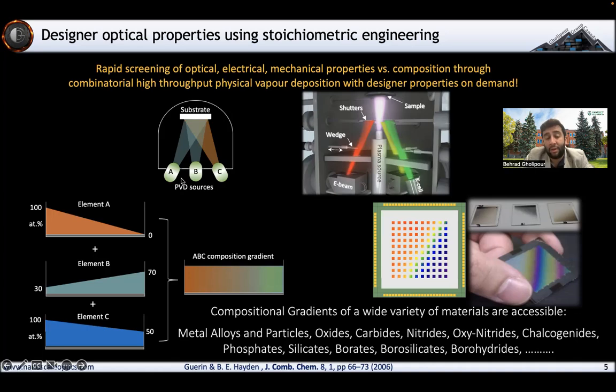So if you have a fictional material system, let's say ABC, by putting these wedges in front of the different sources, you can create different thickness gradients of these materials on your sample substrate. And as soon as you co-deposit all of these together, you basically create a situation where across a single substrate, you've got an alloy being deposited where every single different position has a slightly different composition. So once you've optimized the positions of your wedges, you can come up with a sample that contains 30, 40, 100 different alloys, really, depending on whether you put discrete masks on or you have a continuous film as we have here.